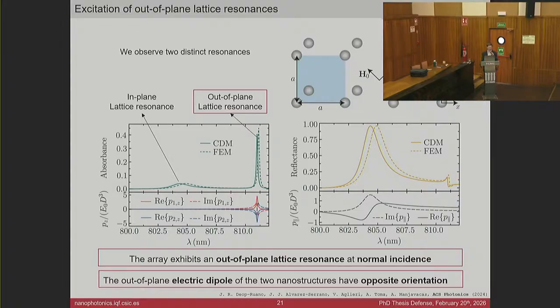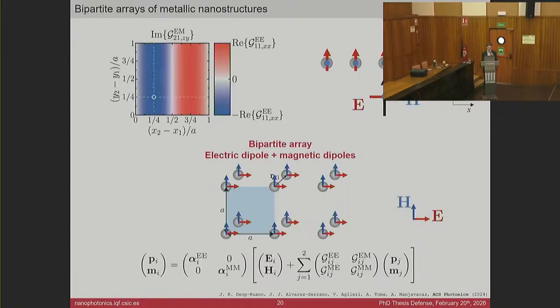This is something really important, and that maybe I forgot to mention in more detail. I was talking about this electric magnetic interaction that is the working principle of our out of plane resonance. And basically, we need to optimize this kind of interaction. Here I only show you the xy component, and you can see that it contains its maximum values along this line, but also this line, but changing sign. And we have to take also into account, but I didn't show it here, that there are more components of this electric magnetic coupling.